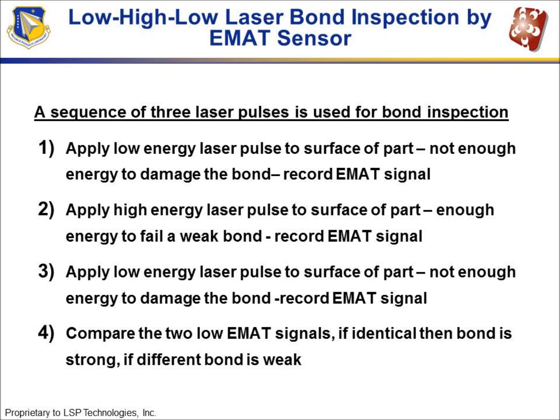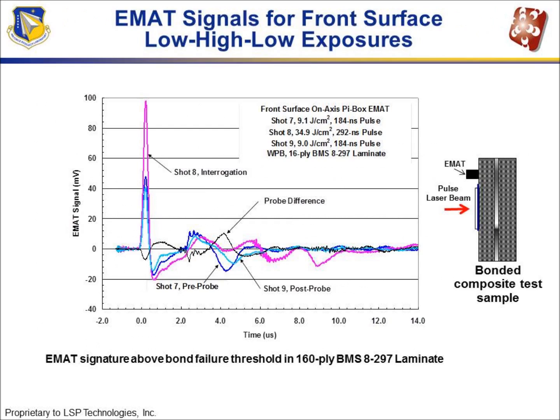To use the EMAT gauge, we use a technique of low-high-low inspections. It consists of 3 laser pulses. First, we apply a low-energy pulse that has absolutely no effect on the bond itself, but it gives you the condition of the bond line before you interrogate it with the strong shock wave. That is a shock wave just strong enough to affect weak bonds, but not strong enough to affect a strong bond. So we do the first interrogation with a weak laser energy pulse, and then we apply the high energy pulse that actually does the interrogation to see if a weak bond exists.